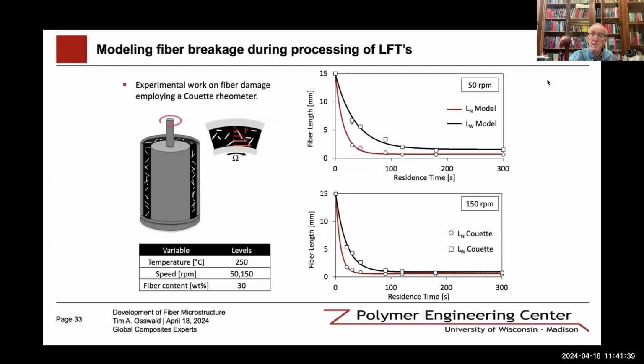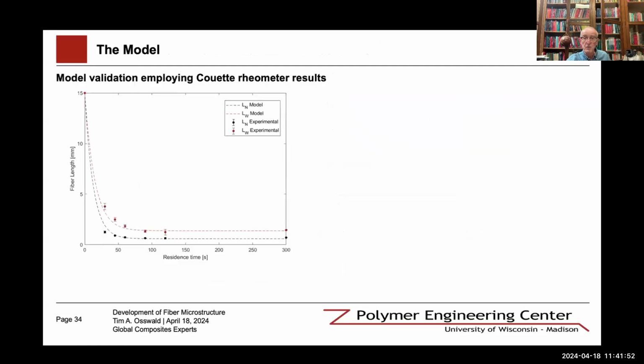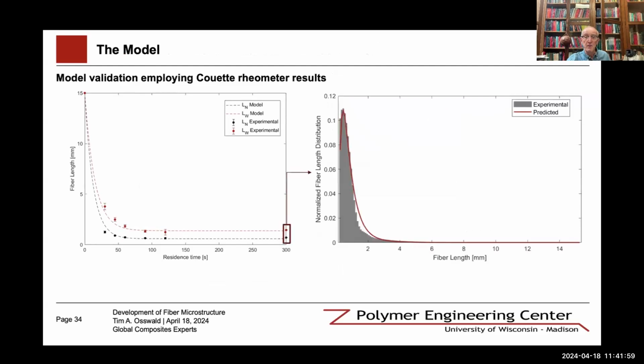For the two different RPMs here, 50 RPM and 150 RPM. The other thing is, when we have the number average and the weight average, those are like the moments of the distribution, we can also then, in this case, if we look at the experiments with the rheometer results, we can also recover the length distribution. So if we have the number average and the weight average, we can with that recover a distribution, which is the measured distribution there in gray that you have.